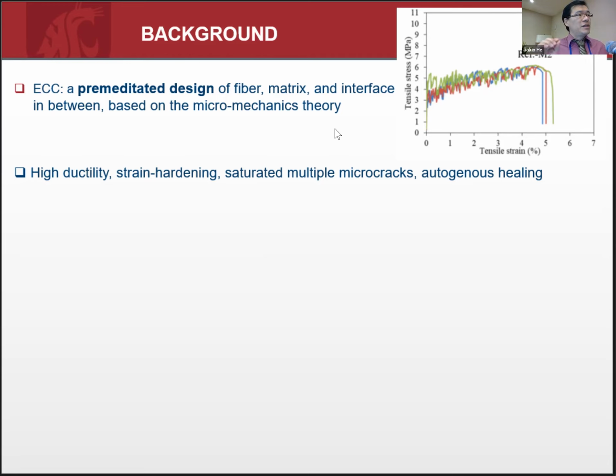And you also have this so-called saturated multiple microcracking behavior and autogenous healing, because usually the width of the cracks is less than 100 microns. Again, the human hair diameter is roughly 80 microns. So instead of having a large wide crack, you have multiple hairline cracks. So it's easier when the material goes through wet-dry cycling, because CO2 from the air reacts with the pore solution in the material and deposits calcite and heals itself.